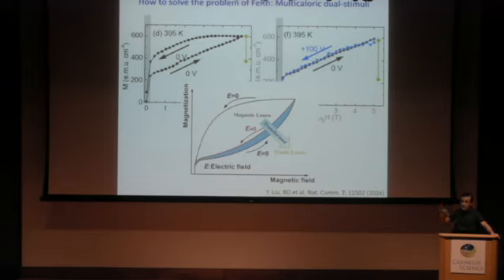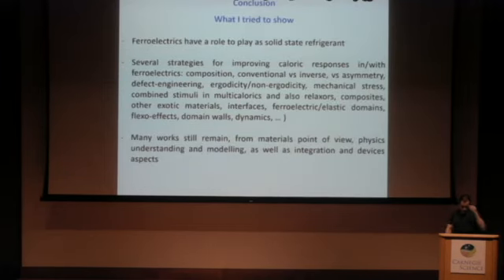But in the end, if we make some calculation, we can see that we have a better efficiency once we use these two works, electric field and magnetic field, rather than only magnetic field. So this is my conclusion. The idea is indeed to show you that we can think about ferroelectrics for solid-state refrigerants. I showed you some of the strategies that we are working on, like composition, conventional, inverse, asymmetry, defect engineering, ergodicity and non-ergodicity, applying mechanical stress.